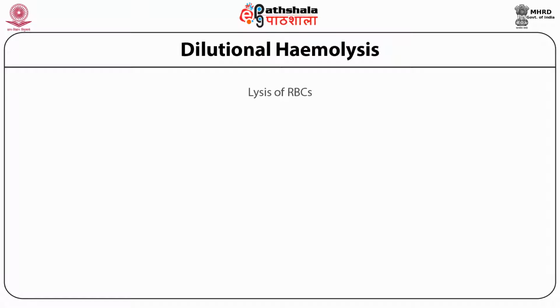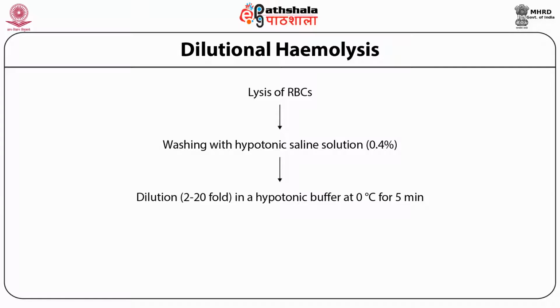Dilutional hemolysis: the swelling and lysis of RBCs upon exposure to hypotonic medium, that is 0.4% weight by volume sodium chloride, may encapsulate a number of drug molecules. One volume of washed cells might be treated with 2 to 20 volumes of the substance to be encapsulated within the RBCs using a hypotonic buffer at 0 degrees Celsius for 5 minutes.